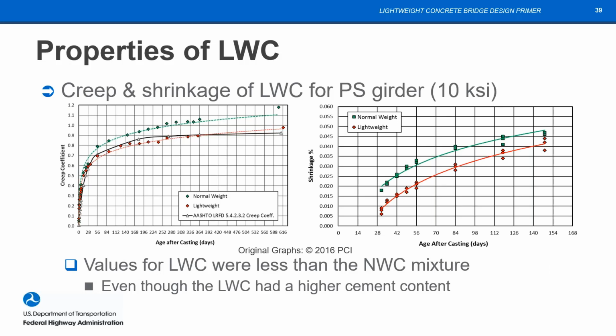Here's some information from the concretes used for girders up in the Northwest. We have creep over here and shrinkage over here, and the red lines are for lightweight concrete. The green line is for normal weight concrete. The creep coefficient is actually less for the lightweight concrete than the normal weight, and the shrinkage is less for the lightweight than the normal weight. What's really interesting, especially for the shrinkage, is that the lightweight concrete mixture has like 24% more cementitious material in it than the normal weight mix. And conventional wisdom is if you have a much greater cementitious content, you're going to have more shrinkage. And this is showing the opposite, actually by a fair margin. So that's the benefit of internal curing.